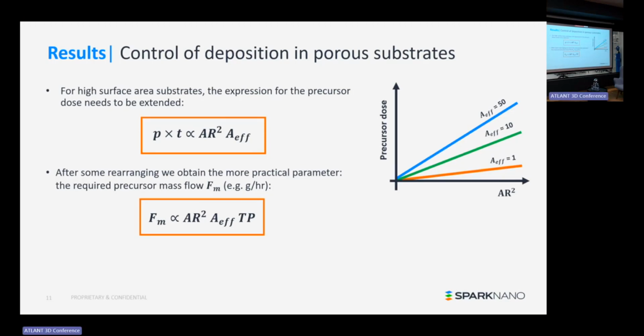Well, you can rearrange this equation a little bit into a more practical parameter, at least from our perspective, which is the required precursor mass flow. How many grams per hour do we need to supply? If you rearrange it, you get something like this, where the mass flow scales with the square of the aspect ratio, the effective surface area, and the throughput. TP stands for throughput, number of wafers per hour, or something along that line. Of course, this makes sense, at least I hope so, because basically what this says is if you go deeper, bigger, and faster, you need to supply more precursor. I mean, that sounds familiar.